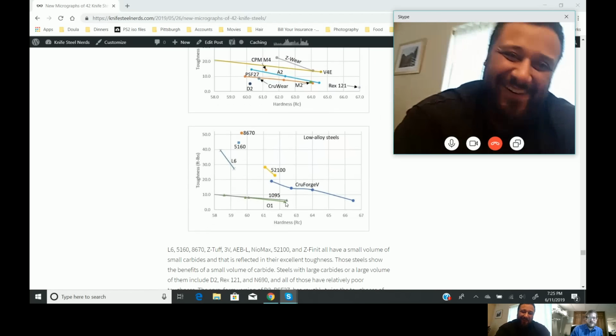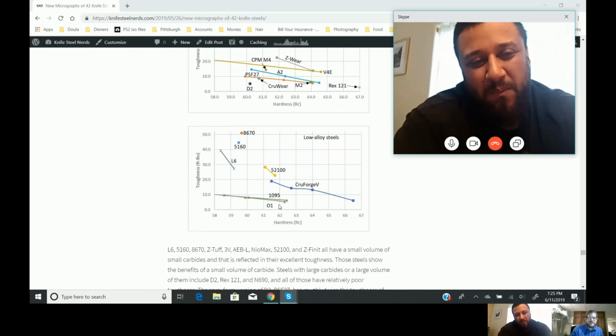But just like I was saying before, the 1095 and 01 are very similar in toughness and not as good as you would think it would be based on their small carbides. 52100 is much tougher. The Cruforge V is a notch below the 52100, but still really good toughness. You know, at 66.5 Rockwell, it's similar in toughness to the 1095 and 01 at 60 to 62.